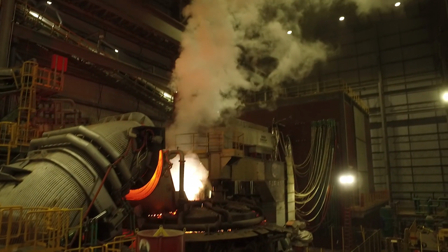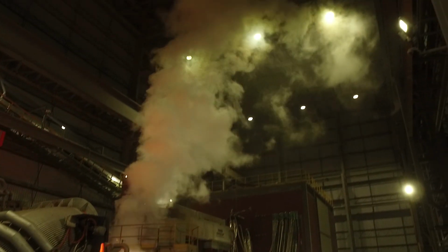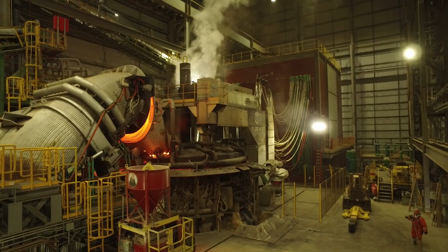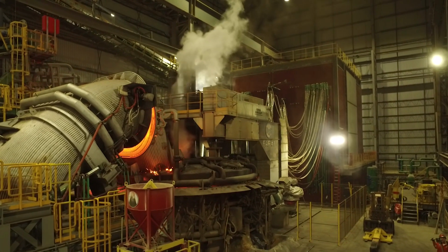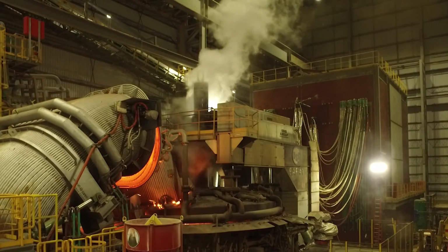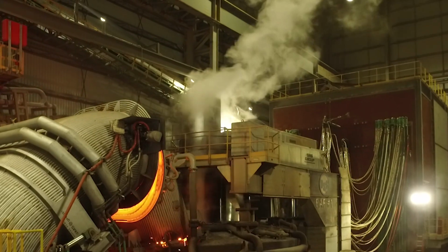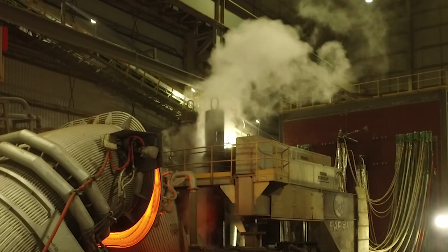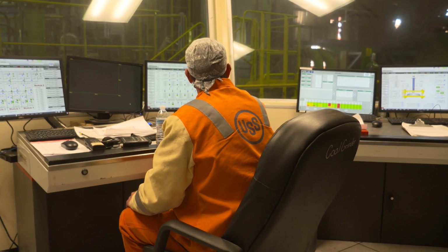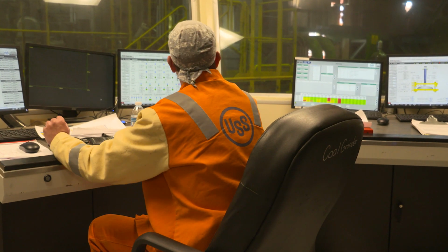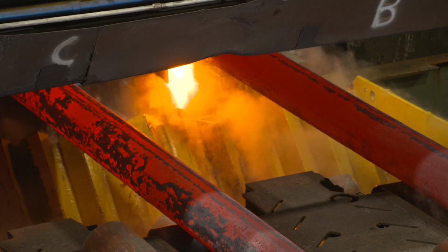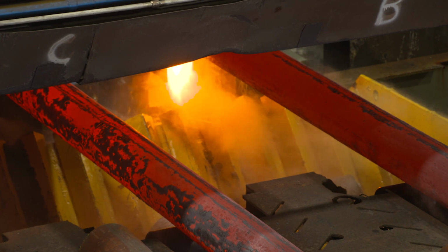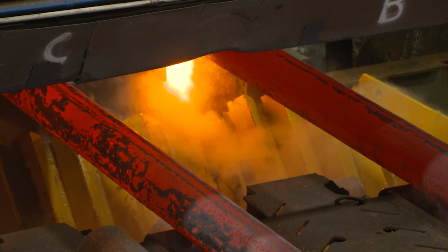The ladle is placed in a tank that is covered with a lid. A series of mechanical pumps draw a deep vacuum on the contents of the tank, including the steel. The ladle is stirred with argon to expose more steel to vacuum. We reduce undesired elements like sulfur, hydrogen, and nitrogen in this process. We also introduce a high level of cleanliness in our steel that is desired for our applications.